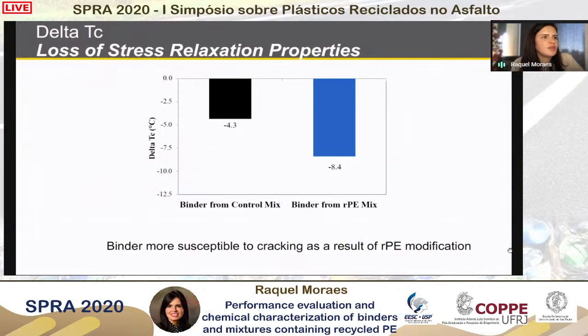And in terms of delta Tc, we can see a doubling in the delta Tc for the binder that was extracted from the mixture containing the recycled plastic in comparison with the binder extracted from the control mix without the recycled plastic, which shows that the binder extracted from the mix containing the waste polymer is much more susceptible to cracking after modification.